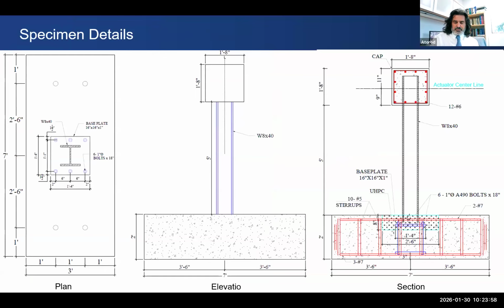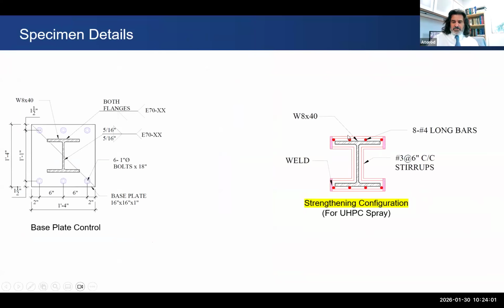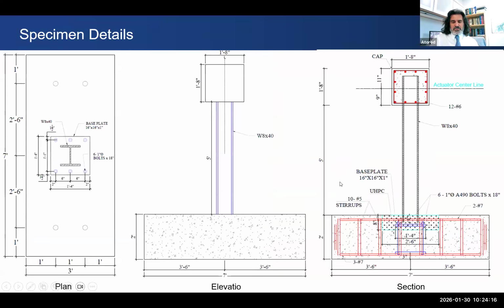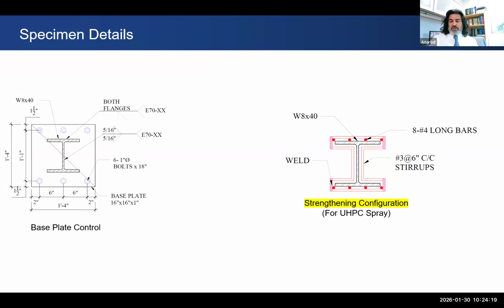But before we do that, you see the cross section, we're going to wrap it with UHPC, but before doing that, we're going to add some longitudinal reinforcement and then also some stirrups in a shape that goes around the column. Then once it cures, we're going to test it. So it's going to be a very interesting test. We'll do at least 2 tests to start with: one, cast the UHPC, and one, spray the steel column with UHPC after placing the longitudinal reinforcement and the stirrups. I've not seen any work similar to this, but it's coming up.